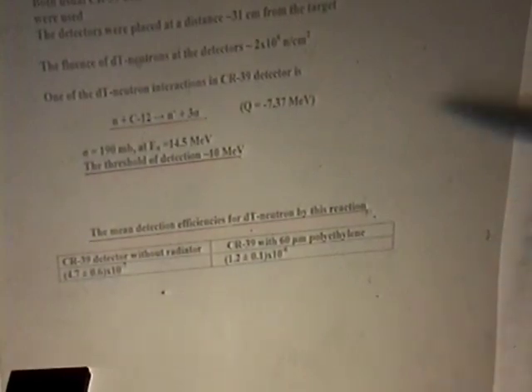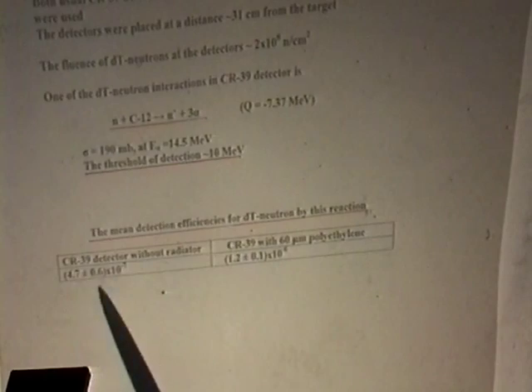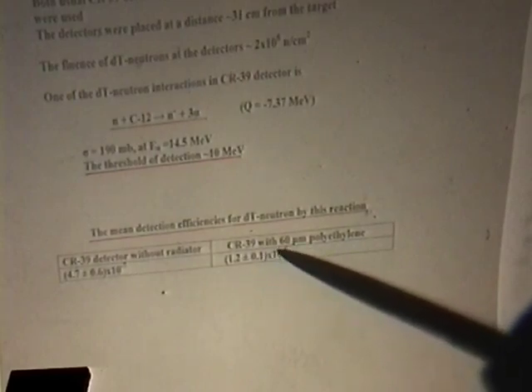We estimate the mean detection efficiency for DT neutron by this reaction as 4.7 plus minus 0.6 times 10 to the minus 7 for detector without radiator, and 1.2 plus minus 0.1 times 10 to the minus 6 for CR39 with 60 microns of polyethylene radiator. The increase of detection efficiency can be explained by DT neutrons interacting not only with CR39 carbon, but also with carbon in the radiator layer.